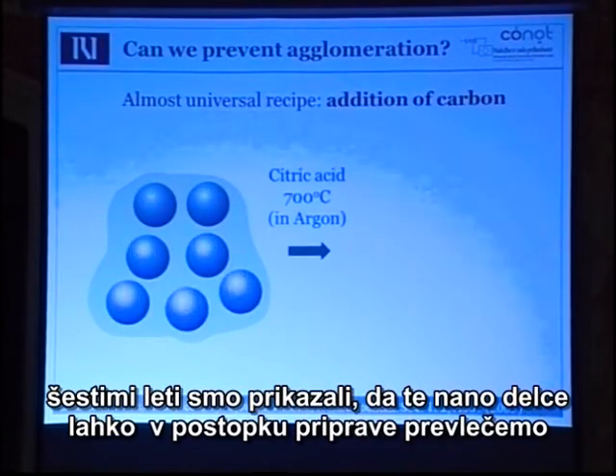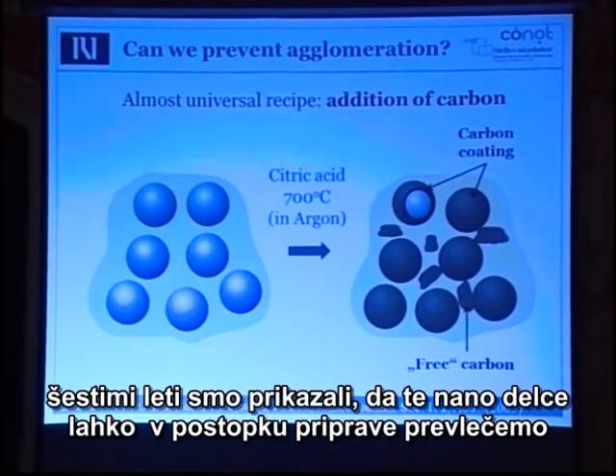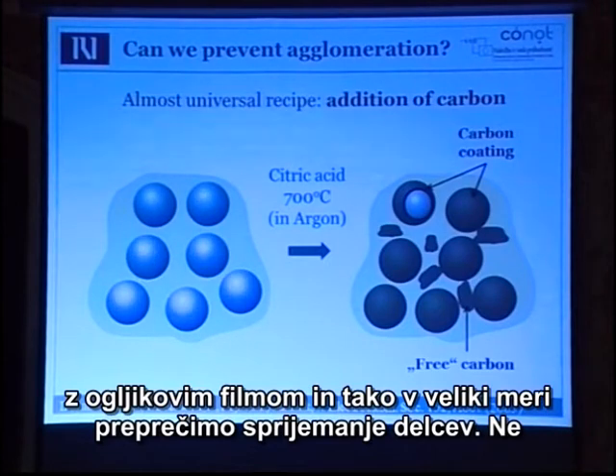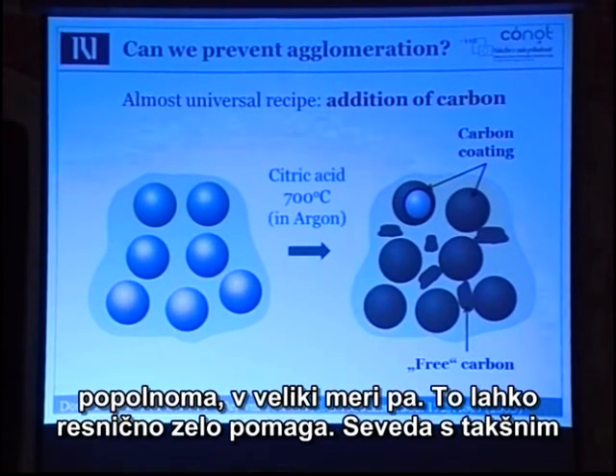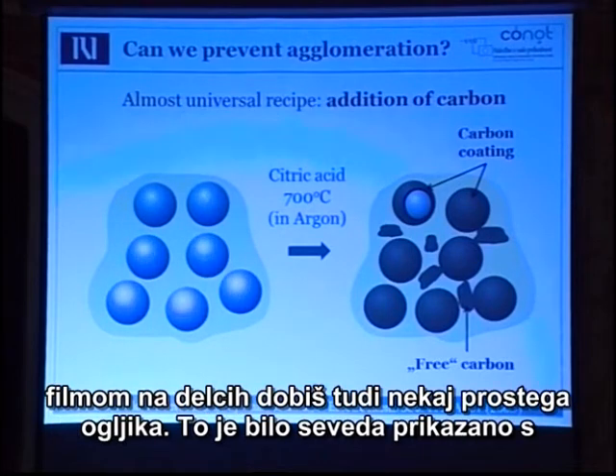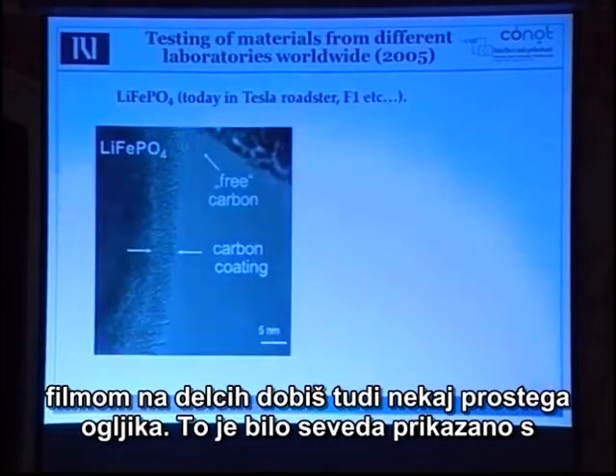We showed many years ago, actually already 6 years ago, that if you put around these particles, during your preparation of these particles, some carbon coating, then you will prevent this agglomeration to a large extent. Not all of it, but to a large extent. So this can be really very helpful. Of course, beside coating, you also get some free carbon and so on.